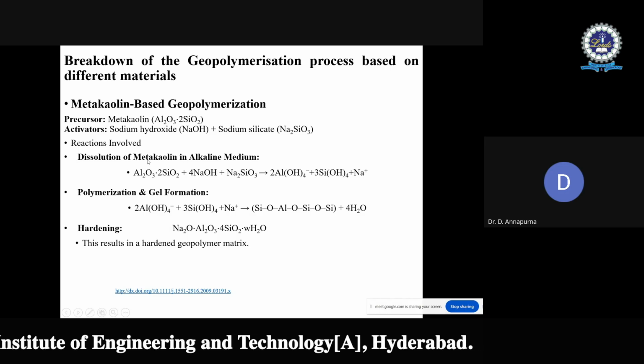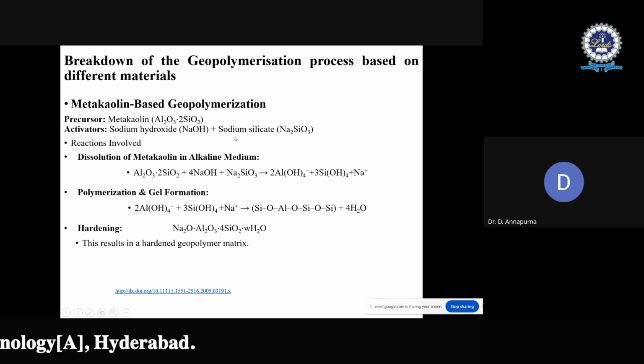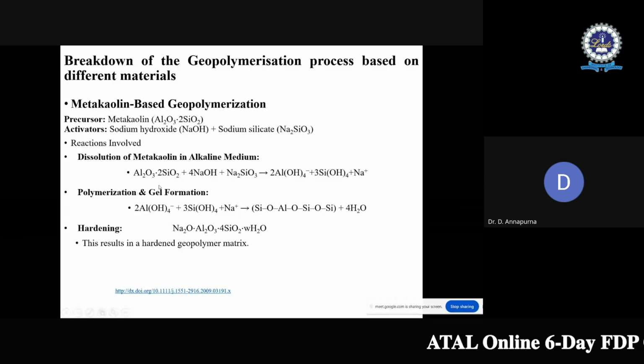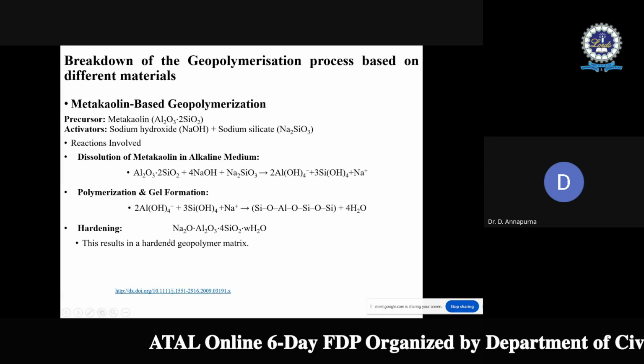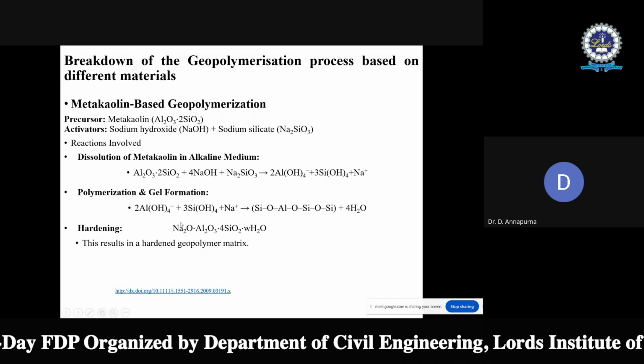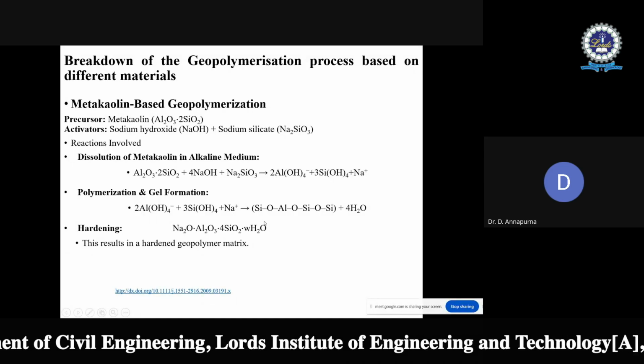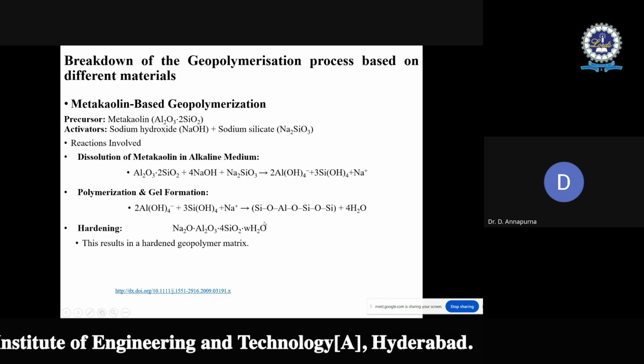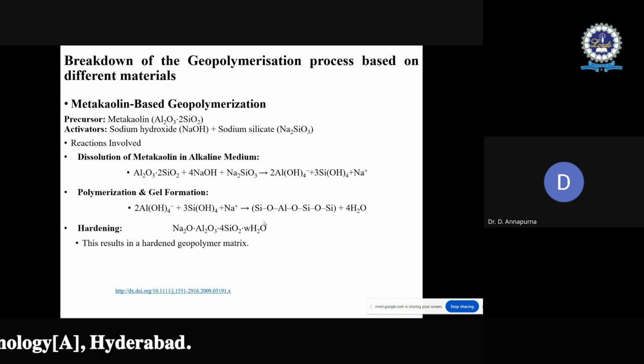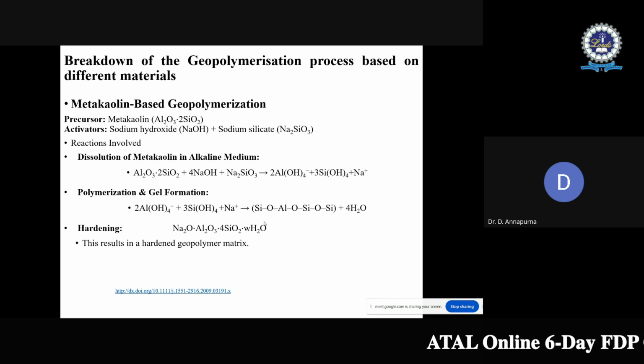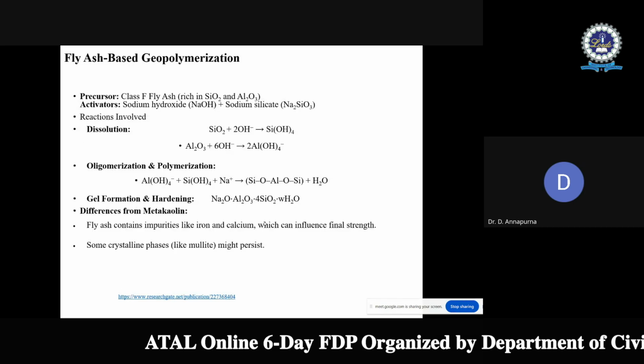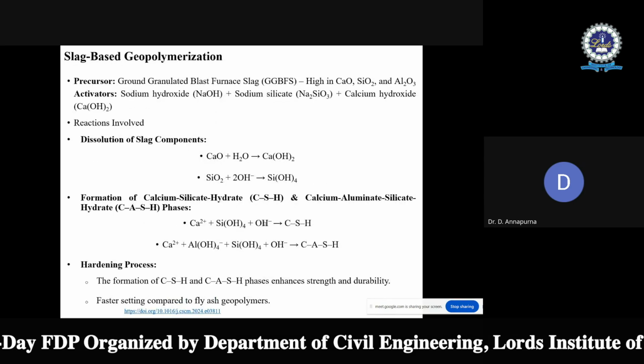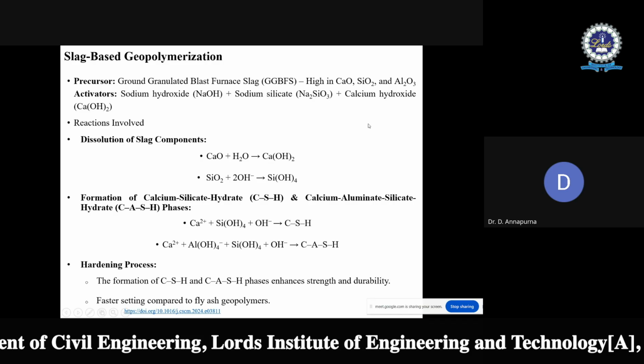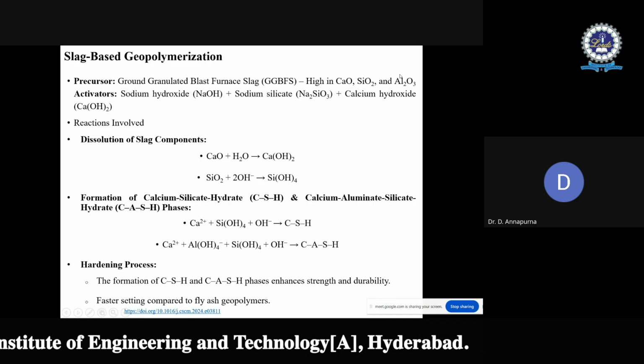So we need to understand first the dissolution of the metakaolin in the alkaline medium. Then immediately oligomerization, polymerization and gel formation will occur. Then the hardening process. When it is hardened, it will give a geopolymer matrix, in the form of NASH. It is common for metakaolin, fly ash, rice husk ash or volcanic ash, sugarcane bagasse, because all are rich in silica and alumina. When it comes to GGBS, ground granulated blast furnace slag has a high amount of calcium oxide, and silica and alumina are also there.